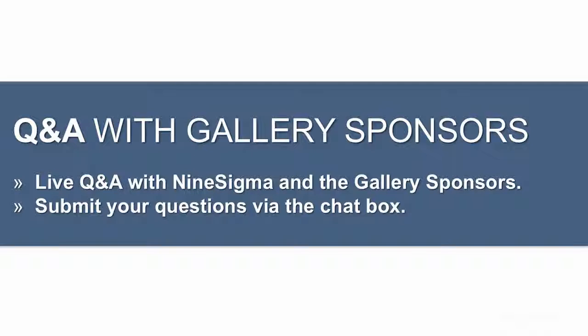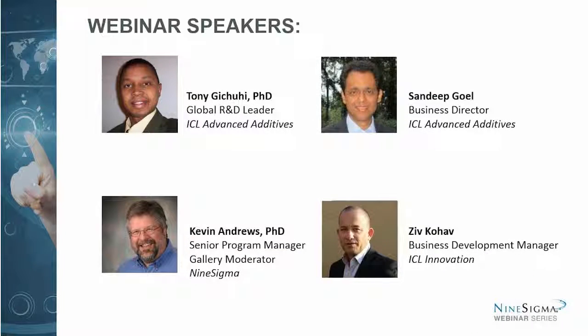And these are the ones I showed in the example, the silicone-type resins or the modified silicones. The film thickness is something that we're concerned about, because most of our customers have told us that the range of film thickness needs to be in the 15 to 25 micron dry film thickness. So this is a criteria that we really need to hit.